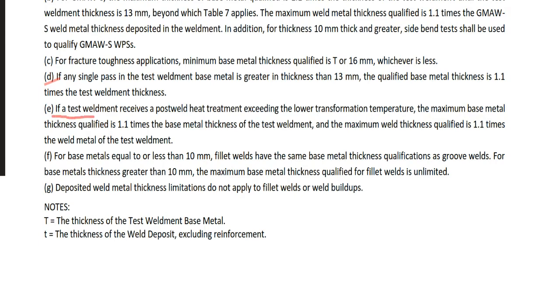If a test weldment receives a post weld heat treatment exceeding the lower transformation temperature, the maximum base metal thickness qualified is 1.1 times the base metal thickness of the test weldment. And the maximum weld thickness qualified is 1.1 times the weld metal of the test weldment. So what it means is here. The test weldment received post weld heat treatment, PWHT. After welding, the heat treatment is applied, but exceeding the lower transformation temperature. And we're talking about carbon steel and low alloy steels, and ferritic steels.